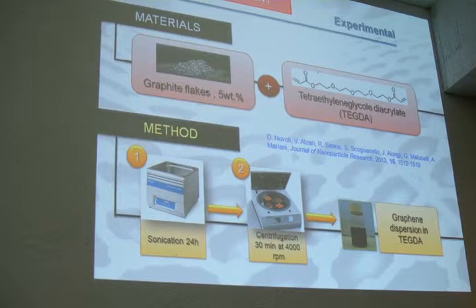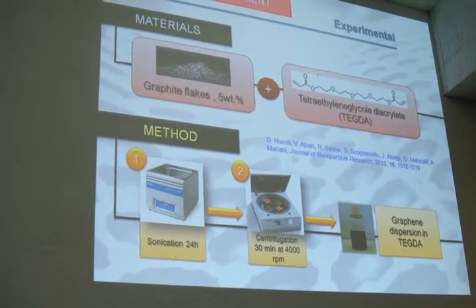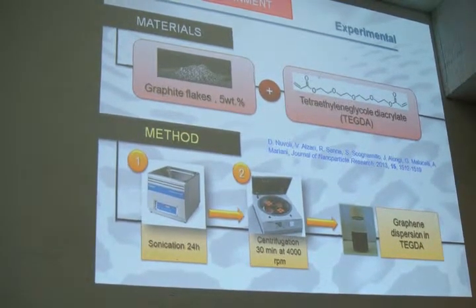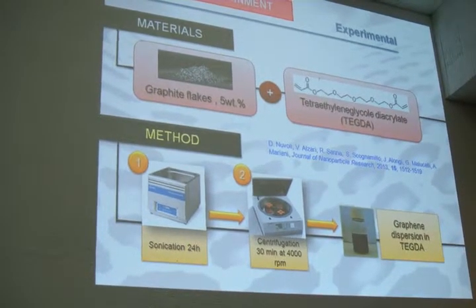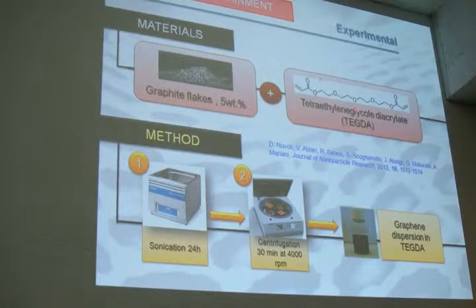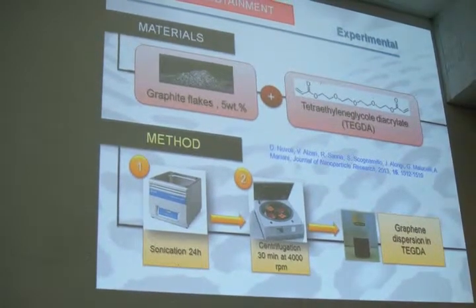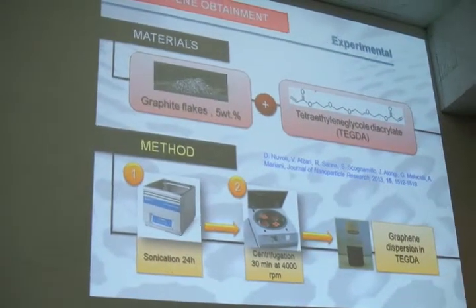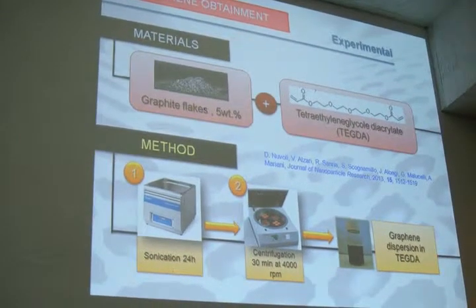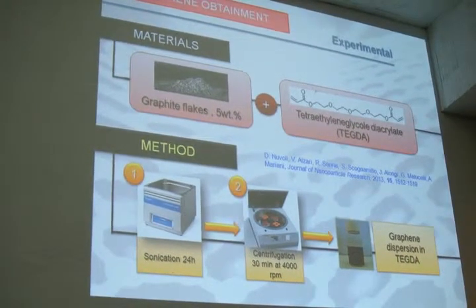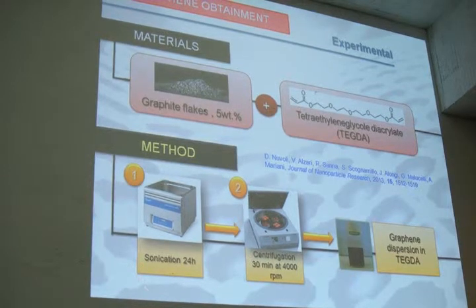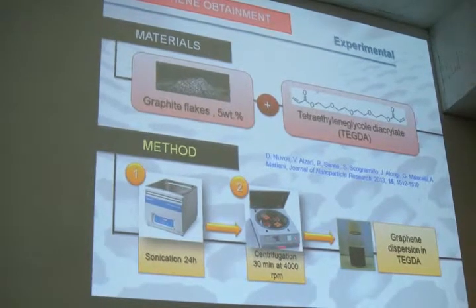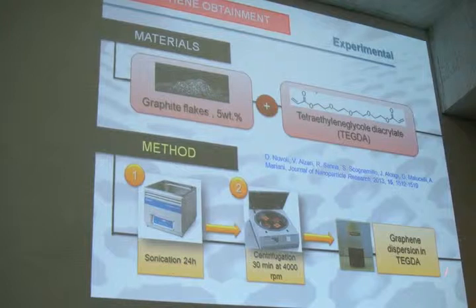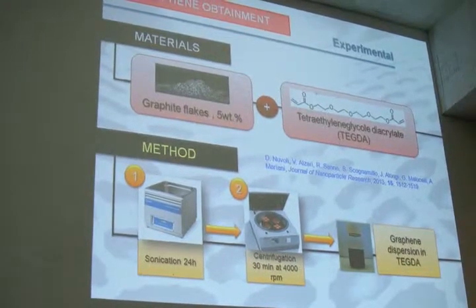The method is very simple, and we tried it in several liquid media. The best we found is this one. It's a monomer. We are interested in polymer nanocomposites, so we try to use monomer if possible. And we just sonicate for 24 hours, then we centrifugate, and what you obtain is a graphene dispersion.